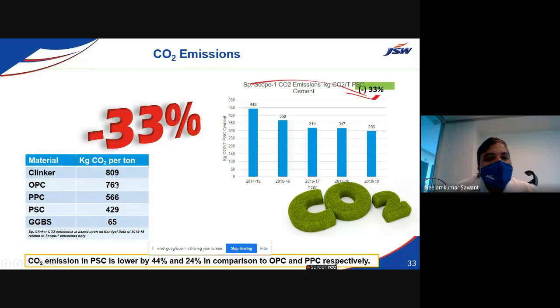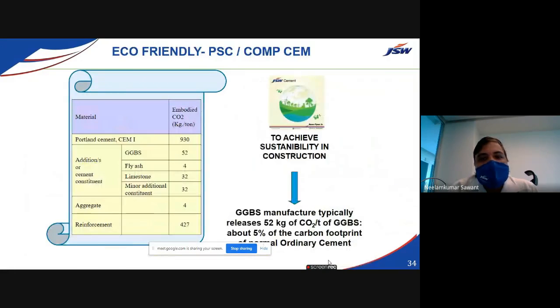So as compared to the OPC, about 50% of carbon dioxide is evolved while processing the PSC manufacturing. So we can imply that CO2 emission in PSC is lower by about 44% as compared to OPC, as well as 24% as compared to the PPC type of cement manufacturing. Eco-friendly product, we can see over here the CO2 certification, and for GGBS manufacturing, generally 52 kilograms of CO2 is evolved. This is one of the test certificate results.